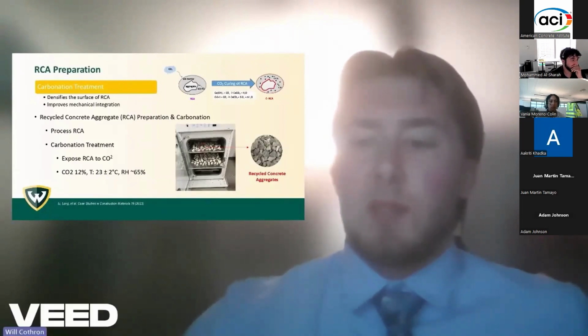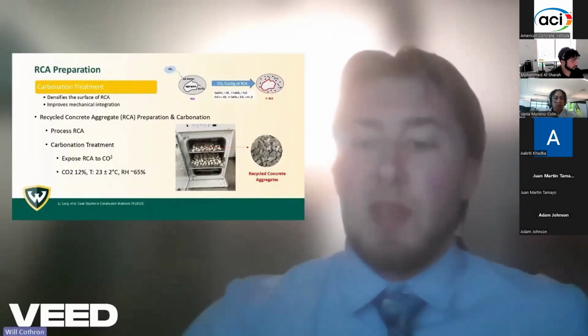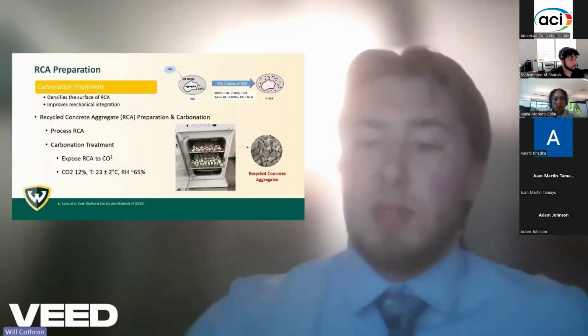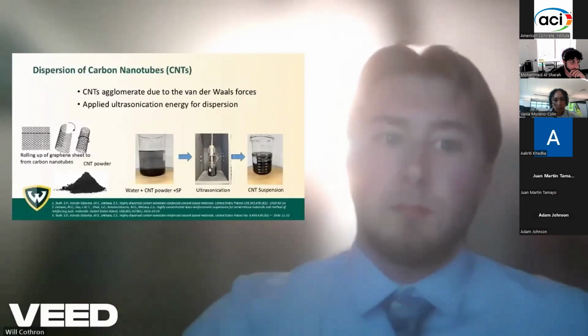This carbonation process allows the CO2 gas to react with the old mortar on the surface of the RCA particles. As shown in the diagram at the top, these chemical reactions form a denser and stronger outer layer by producing calcium carbonate and silica. The photo on the bottom right shows our actual RCA samples undergoing this carbonation treatment in the lab.